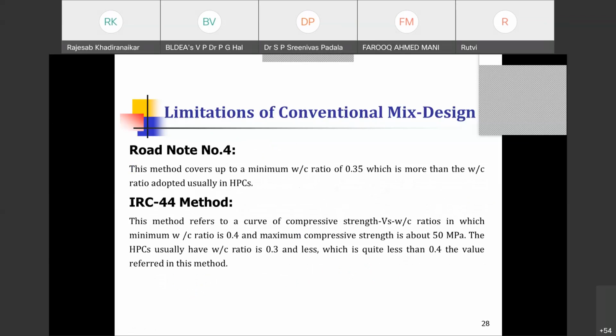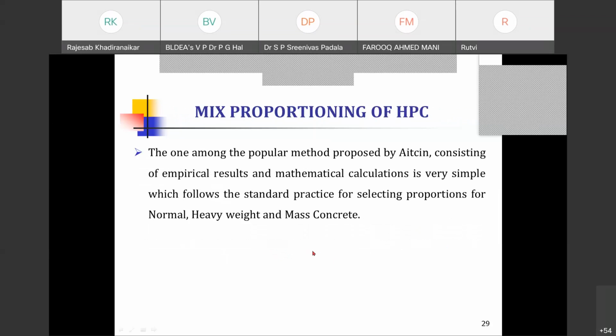Road Note number 4, here also the minimum water cement ratio is 0.35, but we normally go below 0.3. So you cannot apply this. IRC, this was a very popular technique, and here the minimum water cement ratio is 0.4, and the strength is around 50 MPa. Since we are dealing with less than 0.3, we cannot adopt this technique also.